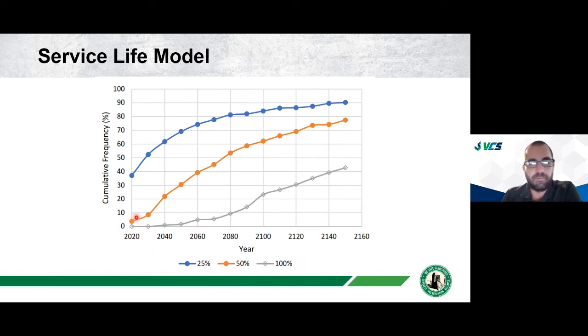Right now, about 5% of the wall had 50% section loss or worse. And we can see how much of the wall will have at least 50% section loss over time. We could see about 50% of the wall with 50% section loss in about 2070. So we can use this model to understand: do we need to replace this wall? Do we need to have cathodic protection on this wall? What's the durability? We can also see when we will have 100% section loss. About 10% of the wall will have 100% section loss in 2080. Using this analysis, we can understand how the deterioration of that wall will occur.